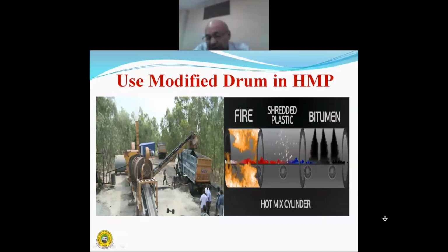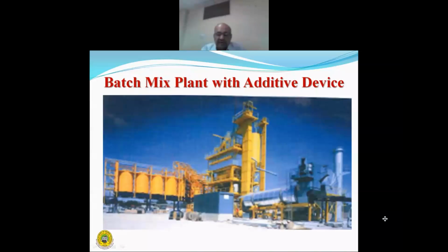Now I am coming to two types of plants that can be utilized for the preparation of the plastic modified mix: modified drum mix plant or batch type hot mix plant. This is a modification of the plant, a mini hot mix plant, where provision is made for adding the plastic over the aggregate in a drum of the drum mix plant.